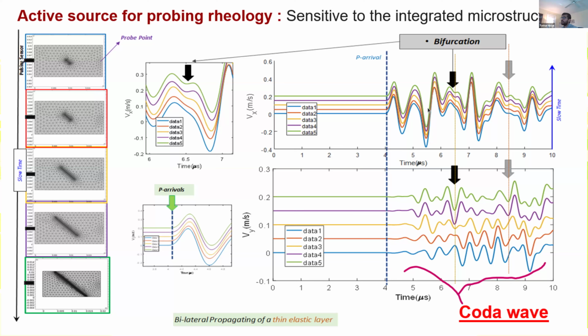If you just focus on the figure on the top, the x-axis is showing time. So what is the probe point receiving over time? The y-axis is showing just the velocity at that location. Each of these colors, the blue, is the sample setup on the top, where we have a small thin elastic layer damage zone. As we increase the damage zone, the P wave arrivals don't change very much. There's a small shift in the P wave arrival potentially, but especially given the noise in real data sets, it's going to be really hard to measure.